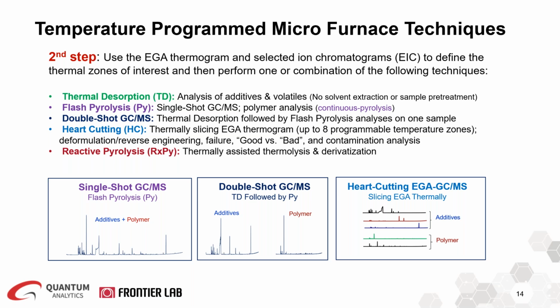You can also perform heart cutting, which is multi-step thermal desorption and pyrolysis. In this case, the EGA thermogram is sliced into multiple temperature zones depending on the thermal profile obtained from the EGA.